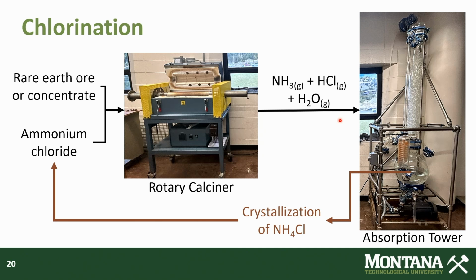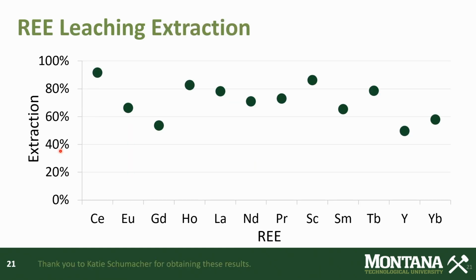This is an absorption tower. We do a lot of adsorption work too, so that's why I'm kind of tongue-tied on that. But this is an absorption tower, so we're just recirculating a stream of water from the reservoir down below up to the top. It percolates down through this packing, and it effectively captures the ammonia and the chloride. So what we can do is take the ammonium chloride, crystallize it, and then return it, because we have to use an excess of ammonium chloride. So this is an economic measure more than anything else.